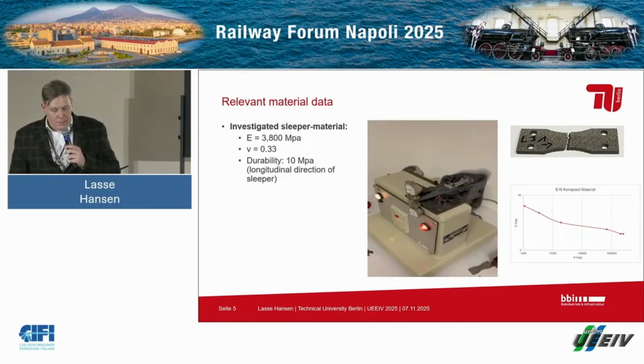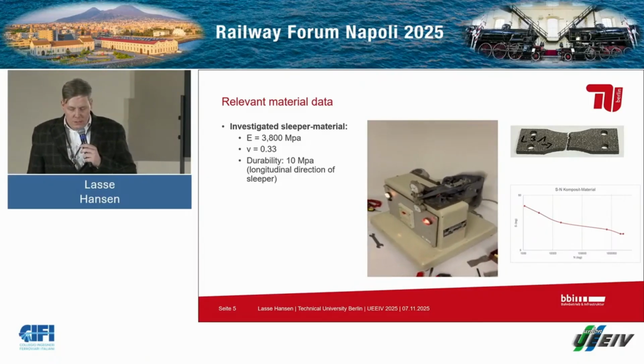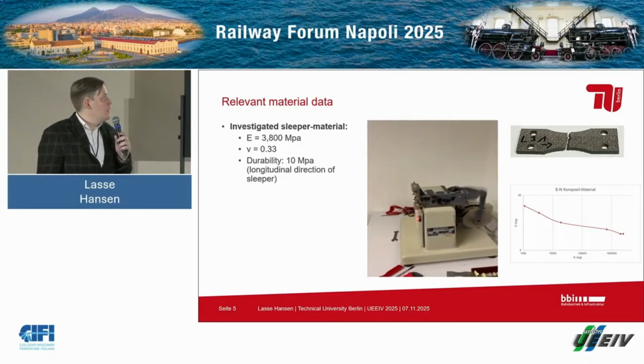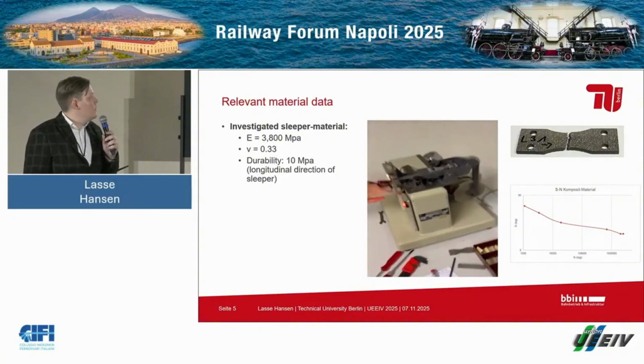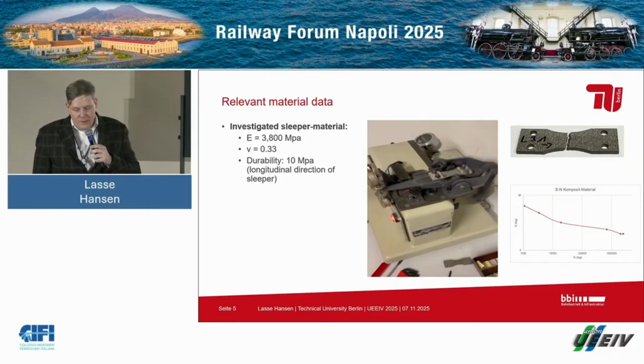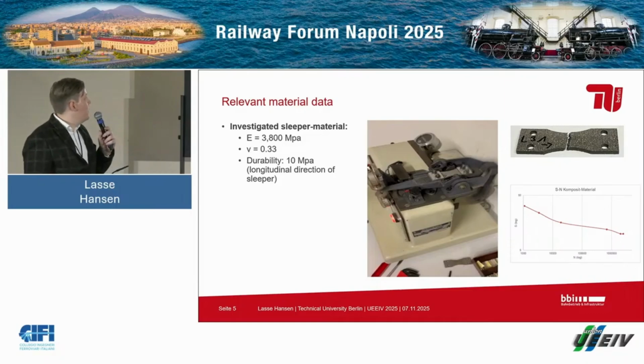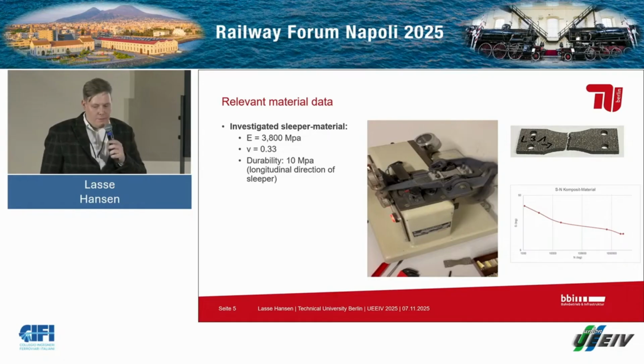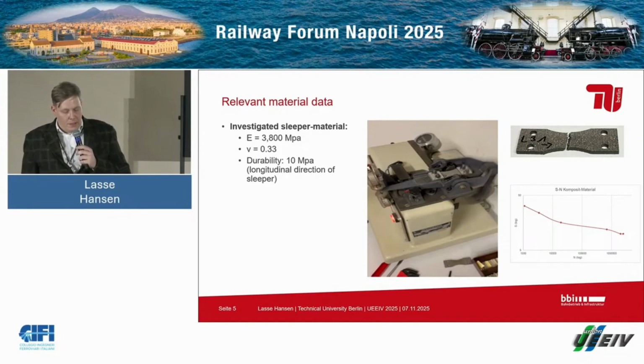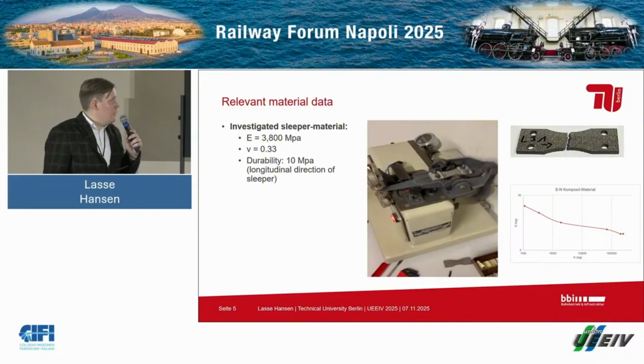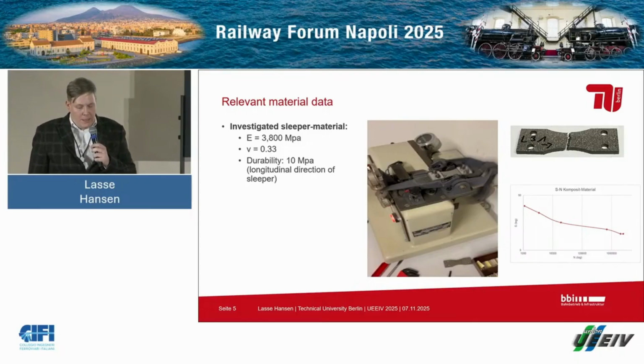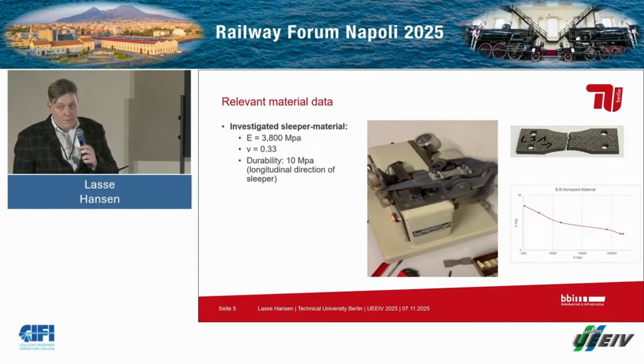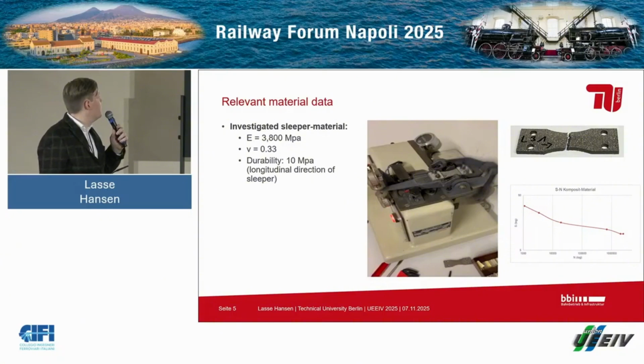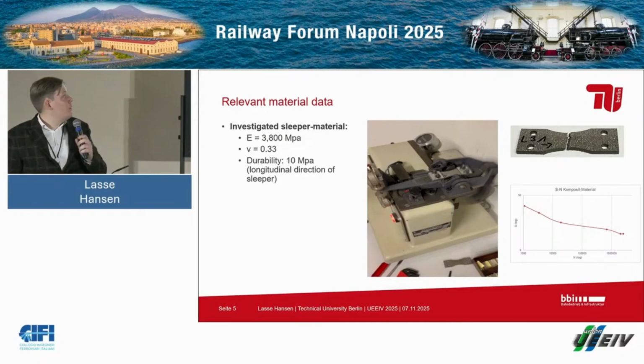Second, the detailed material data. So what we did: we have a material which contains recycled glass fibers out of rotor blades, and also recycled polymers. We did some testing, also dynamic ones, with a specimen, to get the material data. On the right, you can see a Wöhler curve. Our investigated material has an E-modulus of around 3,800 megapascal and a Poisson's ratio of 0.33. And we found out with this dynamic fatigue test that around 10 megapascal is the dynamic durability. So these material data went into the analysis.